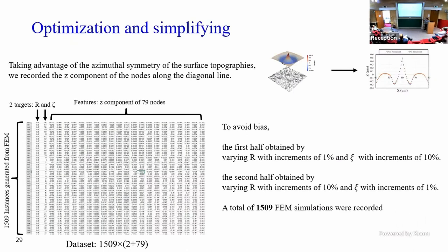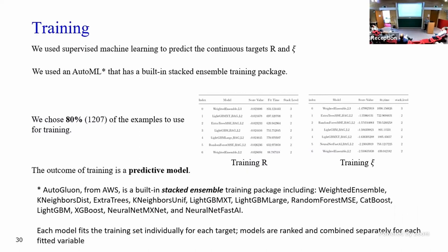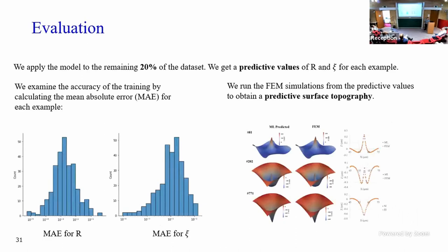So one half of the data, we varied one parameter with increments of 1% and the other one varied by increments of 10%, and then vice versa. So with those 1,509 simulations, then the question is, Angela might ask me, what kind of machine learning did you do? And the answer is, oh, ask Bedell. But it was AutoGluon from Amazon. So it's a stacked ensemble training package and has all these different models in it. Each model fits the training individually for each target, and then models are ranked and combined separately for each fitted variable. We measured how well it worked and compared what was predicted with what was found. And we tried adding noise and showing that the system could still find the appropriate value.